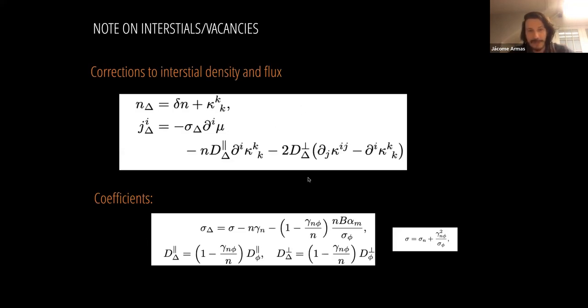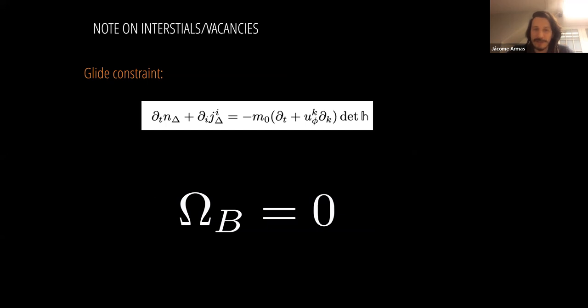Now, you can also, given these definitions, see what kind of effects you get in these interstitial currents. You can define them in this specific way. It's given in terms of these coefficients, D transverse and parallel, and it's completely given in terms of Goldstone diffusion. So Goldstone diffusion basically controls the diffusion of interstitials in the crystal. The reason why we know this very well is because we can map this whole system to the work of Zippelius, Halperin, and Nelson from the 70s and 80s. So like I said before, requiring this interstitial current to be conserved, which means that basically you cannot densify the volume element of the material, implies that one of these relaxation coefficients has to vanish. This is what the glide constraint gives you.